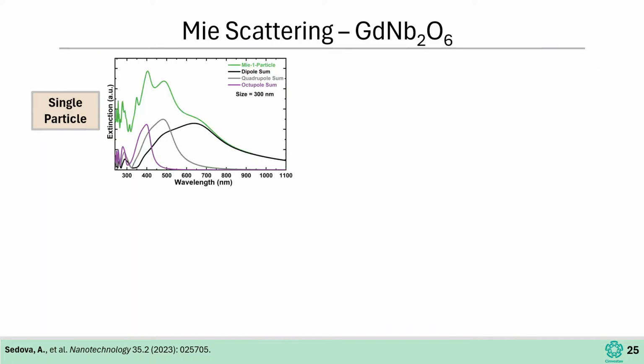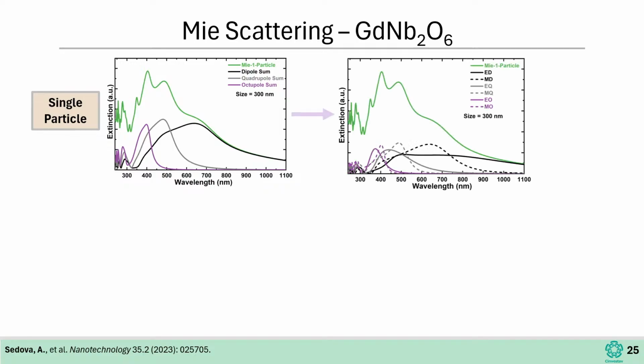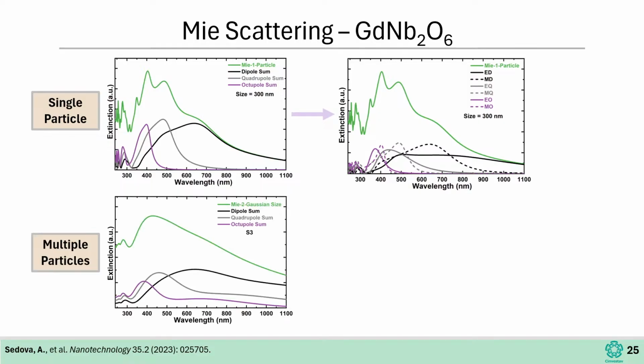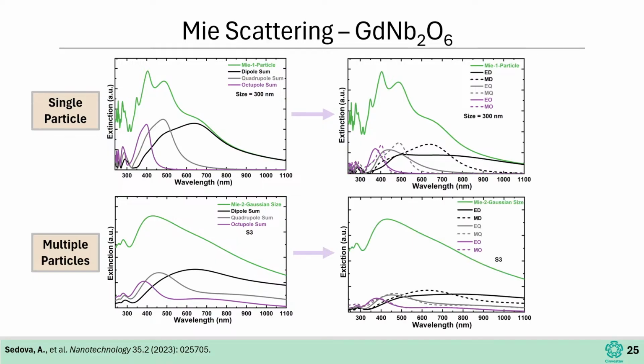We did numerical calculations to see what contributes to this Mie scattering phenomenon. We did it on single particles, and we could see that there is a contribution of the dipole, quadrupole, and octupole. We calculated the electric and magnetic contributions, and we saw that the contributions are different for a single particle. We did the same thing for the multiple particle case. Also here we could separate the contributions of the dipole, quadrupole, and octupole. Nonetheless, when we calculated the separate contributions, we saw they're quite similar in this case. So basically what we have here is the common phenomenon, an average phenomenon of all the particles of all the sizes.